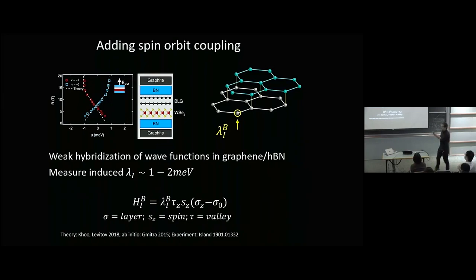It's not the same in every sample, because that actually depends on the angle between the graphene and the WSe2, but you can measure it. You can know the number from sample to sample. Okay, so you can see what it looks like without spin-orbit coupling, and then you can add it and you can know how much you've added. So you know sort of what your single particle Hamiltonian is.